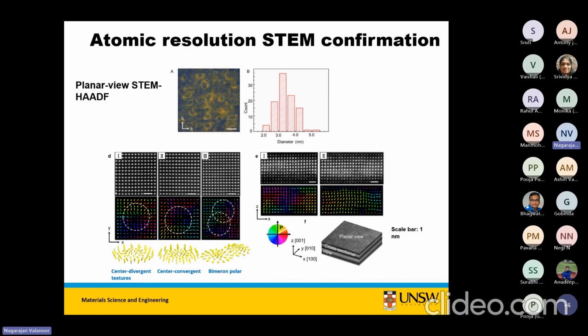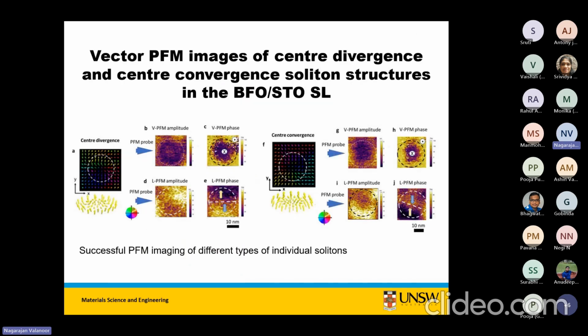So we actually showed in the paper, in the supplementary section, there's a lot more information than this paper. You see there are so many sections. We've shown different kinds of domains. It's all over the sample. Now, final piece, and this is really incredible PFM quality, but sadly, this is in the supplementary information of the paper: Peggy, the postdoc, was able to image different types of individual solitons and show that we have indeed center divergent and center convergent kinds of structures. And that length scale is of the order of 20 nanometers.